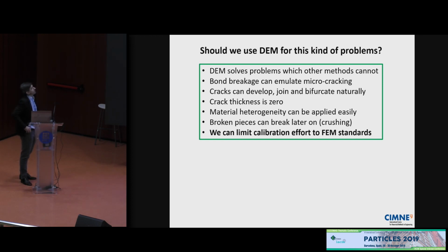So these are basically the conclusions. This bonded DEM solves problems which other methods cannot. The bond breakage can emulate micro cracking. The cracks can develop, join, bifurcate naturally. Then you have contact. Then you have friction. You can add as many parameters as you want, like the rolling friction, rolling resistance. Material heterogeneity can be applied easily. You can change the properties of each particle. Broken pieces can break later on. That would be the crushing effect. And we can limit calibration effort to FEM standard. That's probably the main idea I want to transmit.